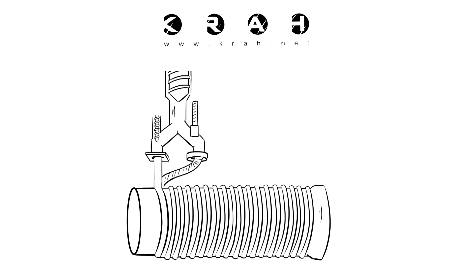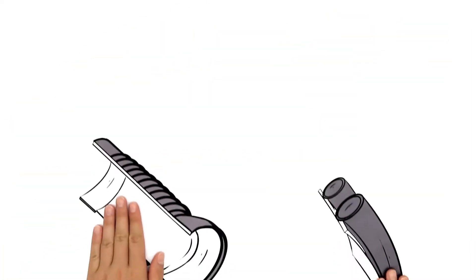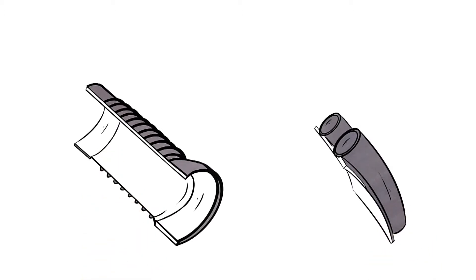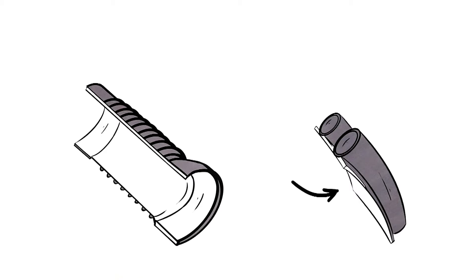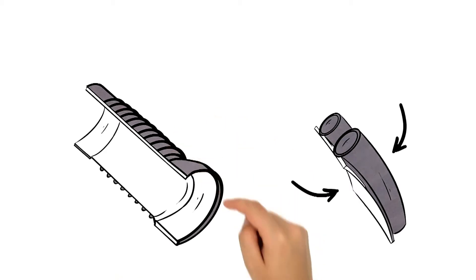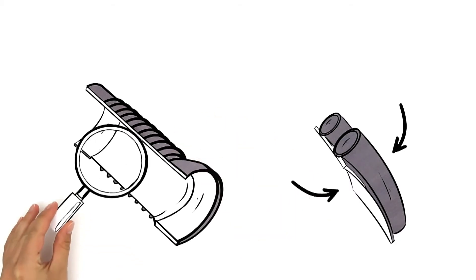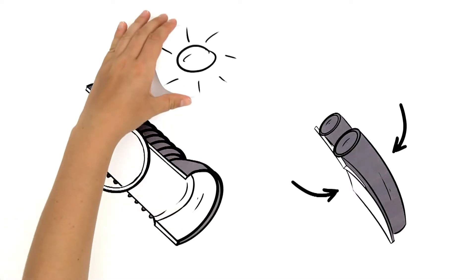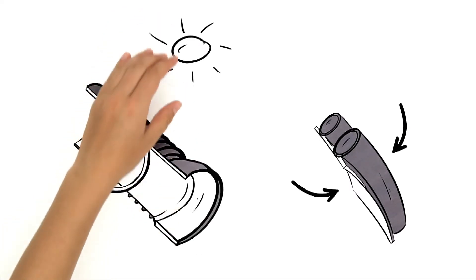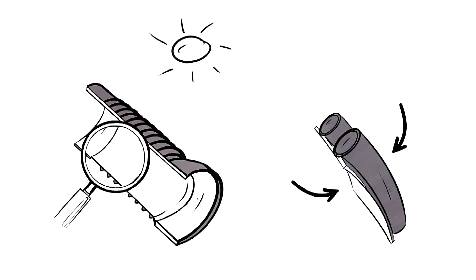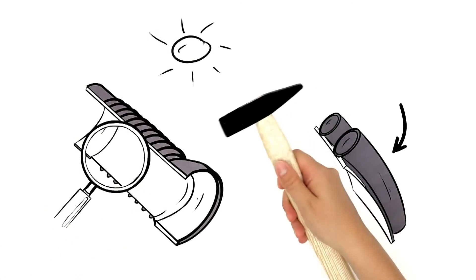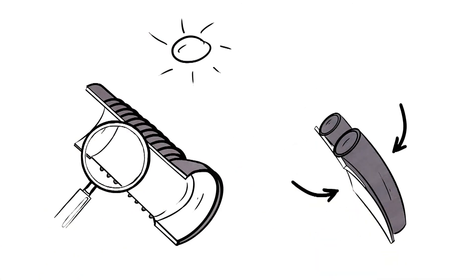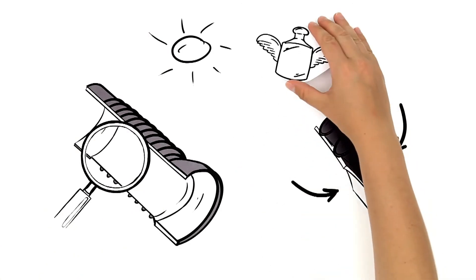When wound, the hot plastic band fuses into a pipe. The band is usually bicolored and profiled. The pipe thus has a light color on the inside and a dark color on the profiled outside. The light colored inside permits easy inspection later. The dark colored outside protects the pipe against direct sunlight, and the profile guarantees high stability at a simultaneously low specific weight.